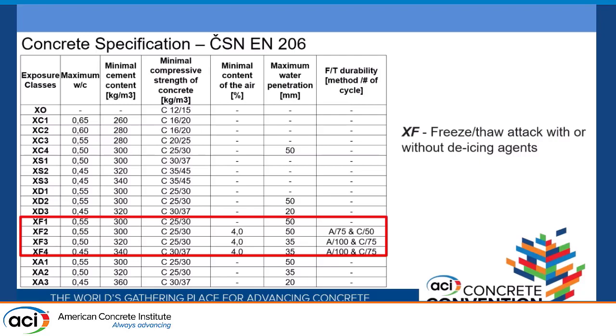And I would like to point out the XF class, which is freeze-thaw attack with and without de-icing agents. If you look at the specification, this class is driven by the water cement ratio, minimum cement content, compressive strength, air content. There is a maximum water penetration that you have to meet, which is, in my opinion, a very, very important thing, because water is good for the hydration, but it's not very good for the durability of the concrete. And then also freeze-thaw durability, the number of cycles that you have to test on the concrete.